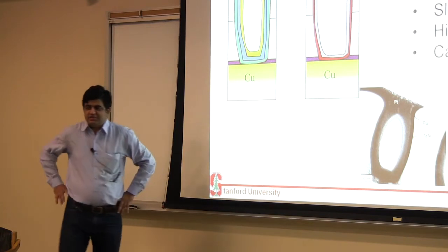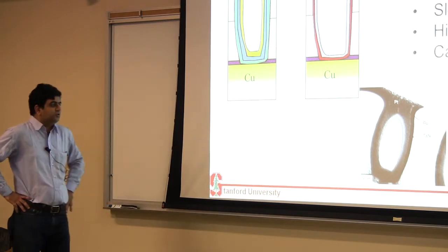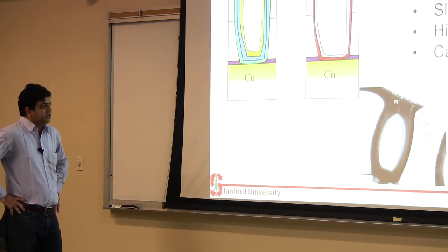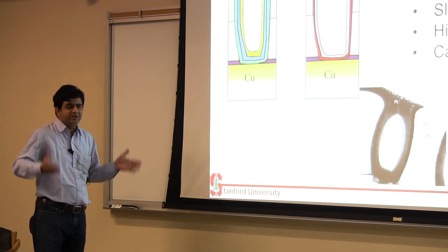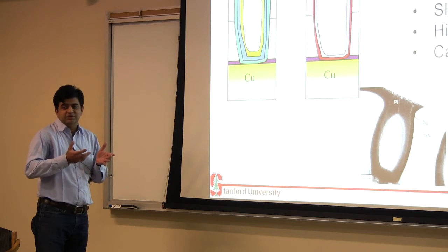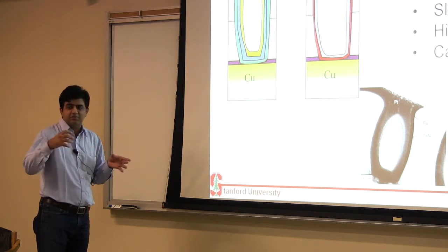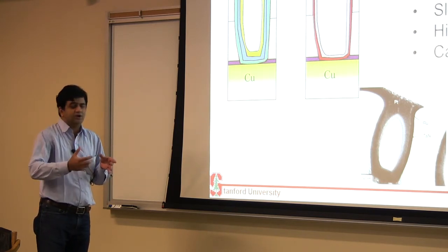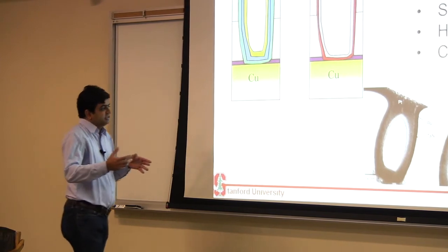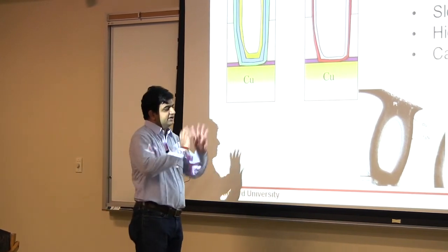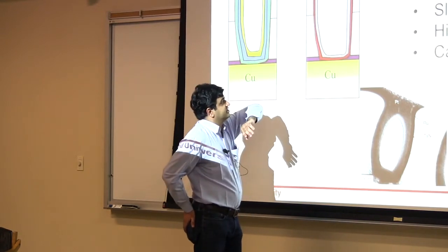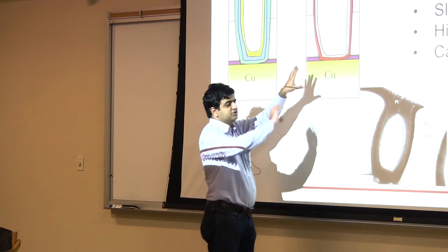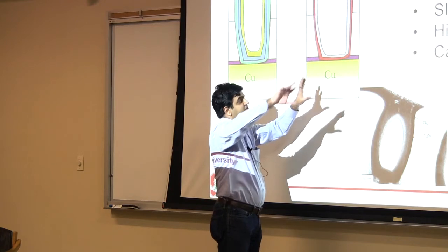most of the metals are solid, right? So if you want to do an ALD of a metal, you have to make a precursor which makes this metal evaporate. So what you do is you attach these carbon groups, your ligands, to your metals, and essentially you evaporate that metal, bring it to the surface of this structure, and then you want those organic groups to leave.